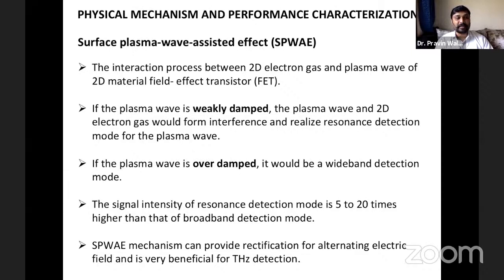But in this case, if your plasma wave is weakly damped, then the plasma wave and the 2D electron gas form interference, and they realize the resonance detection mode for the plasma waves. But if the plasma wave gets overdamped, then a wide band detection mode is observed. The signal intensity of the resonance detection mode is 5 to 20 times higher than the broadband detection mode. Okay. So the signal intensity in the case of resonance is quite high.